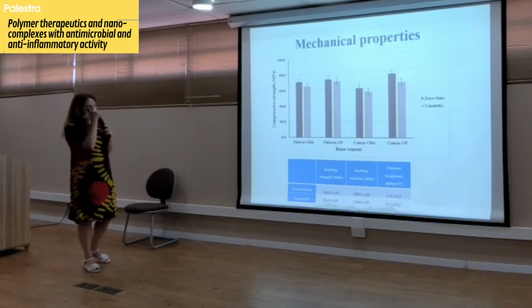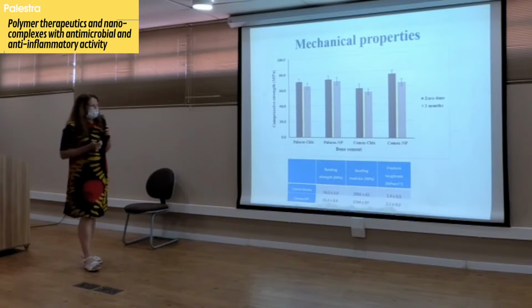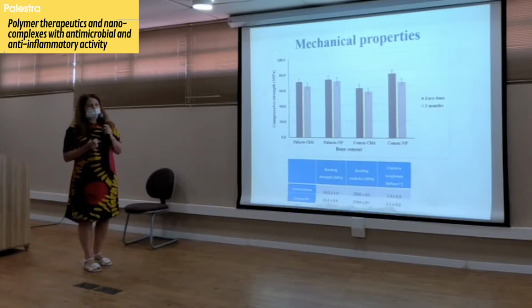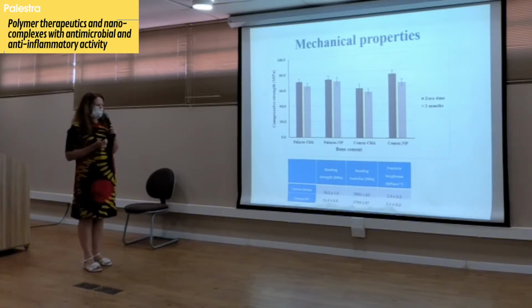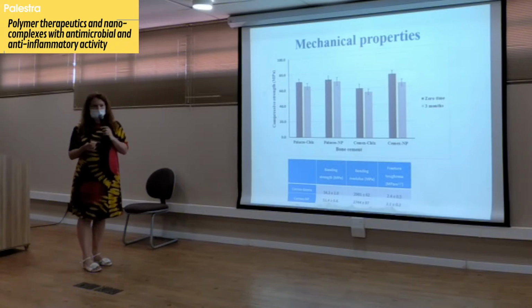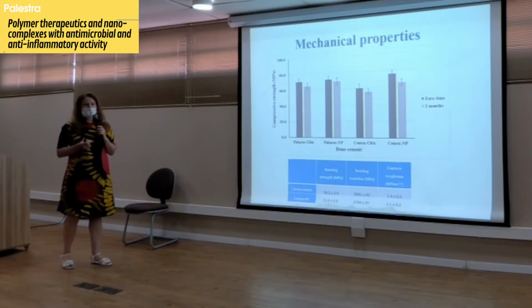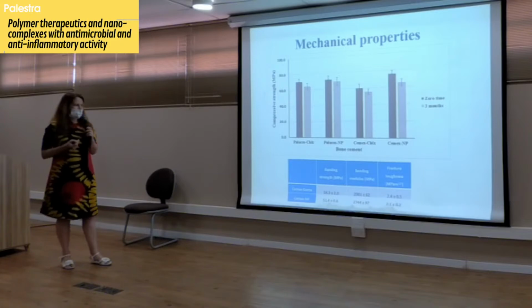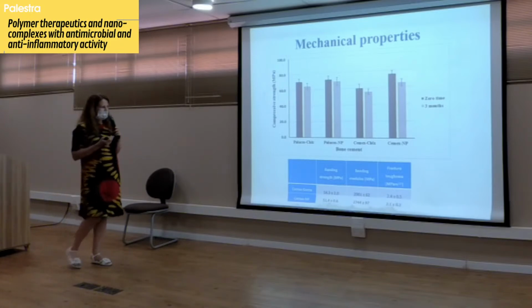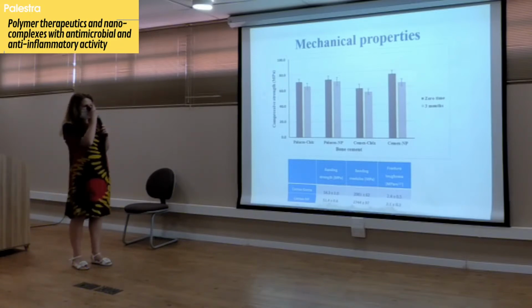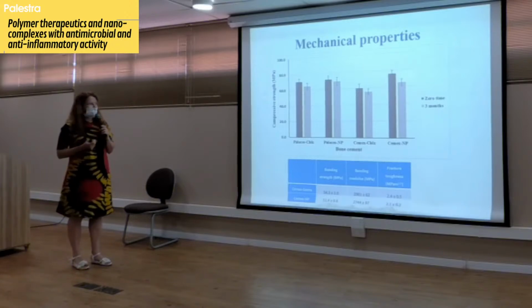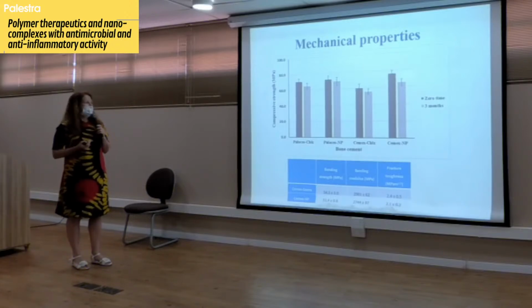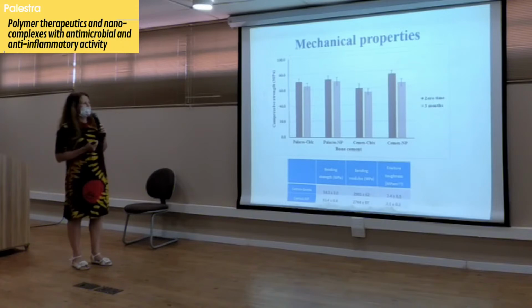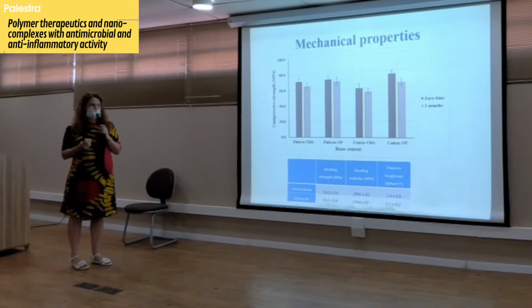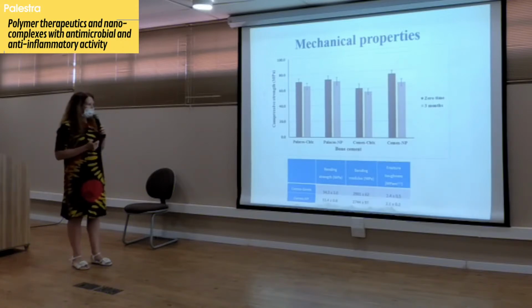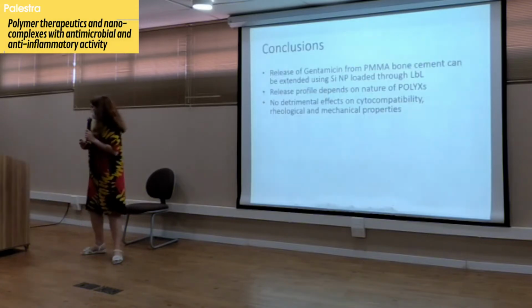We also looked at the stability. So we looked at what happened with the bone cement once it's immersed in a biological fluid for a period of 3 months. Because obviously, the cement is a porous material, and with swelling of the material, you would think that mechanics will drop. We expected that. It did drop, but it dropped within the ISO standard limits. So it was still within the limit, which was good.